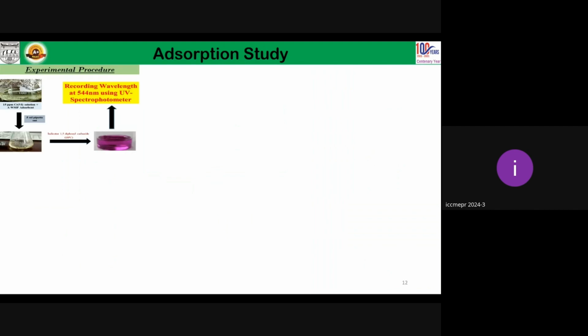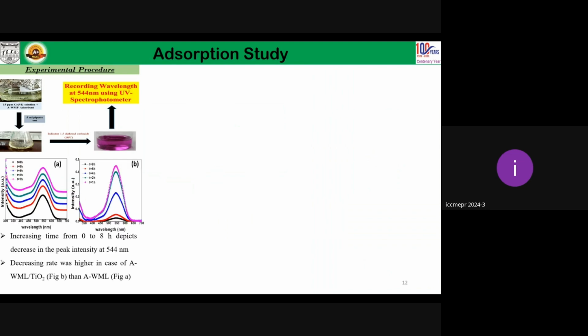Now the performance was studied using a batch experiment. A chromium sample was prepared, into which adsorbent was added, and then DPC was added, and then the chromium concentration was analyzed using a UV spectrophotometer at a wavelength of 544 nanometers. Figures A and B show UV spectra of chromium concentration at different time intervals, and from here it can be seen that the decrease in intensity in figure B was very much higher than in A. Figure B is in the presence of the nanoadsorbent, while A is of the adsorbent material only.